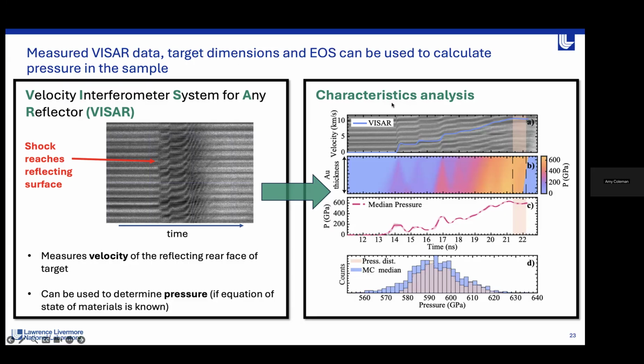I'm showing an example of this characteristics analysis, taken from our gold PRL paper. There's quite a bit of information about this in the supplementary material if you're interested to learn more. Essentially, we run our characteristics analysis, and this gives us a view of the pressure distribution within the gold state during the experiment. It gives us an idea of the median pressure in the sample state during the experiment, and we also have a distribution of the pressure states.